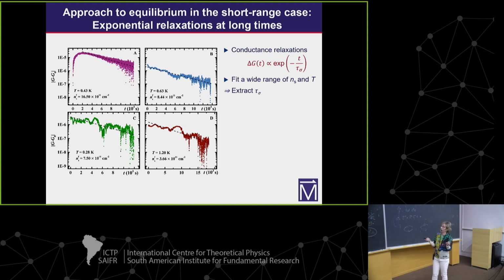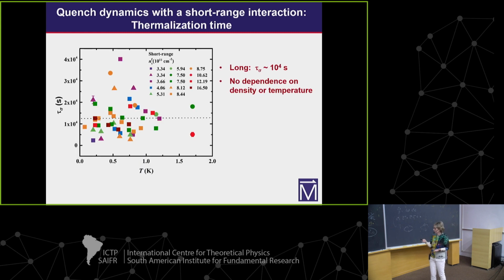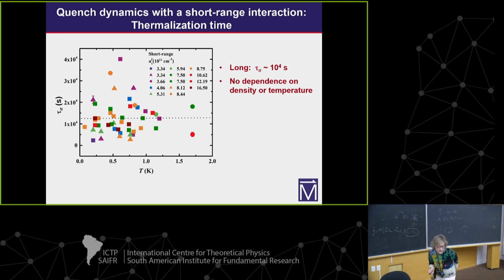Again, we looked at the approach to this stationary state or equilibrium value, and we could fit these curves with a simple exponential function, extract this time, and we do it for different densities and temperatures, and this is what we get. We do not see, the time is long, it's like 10,000 seconds, but there is no systematic dependence on temperature or density or sample size or anything like that.